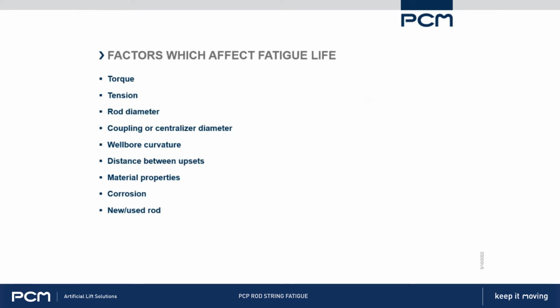Material properties, this basically refers to that SN curve. Every material will have its own SN curve, and that obviously affects how high that graph is, meaning the stress level, and you'd like to have a very small slope on it, so it goes out to very high cycles. That would be good, but every material is different. Corrosion affects fatigue. I'll have an example of that in a minute. And then new versus used rod.